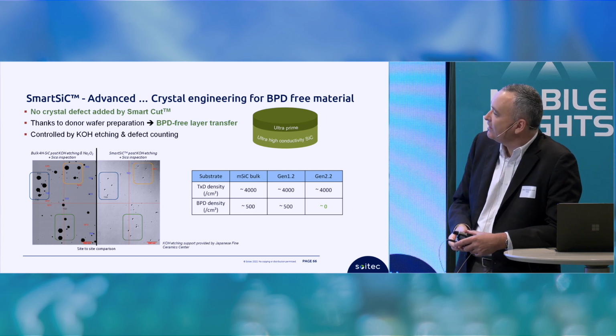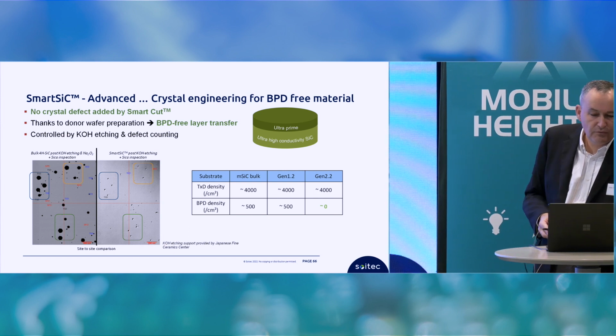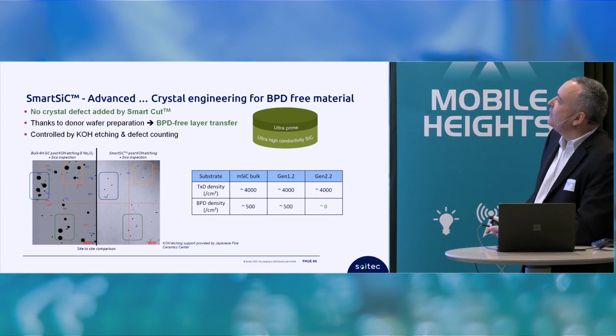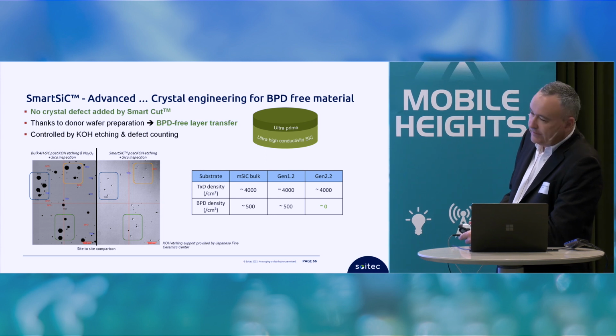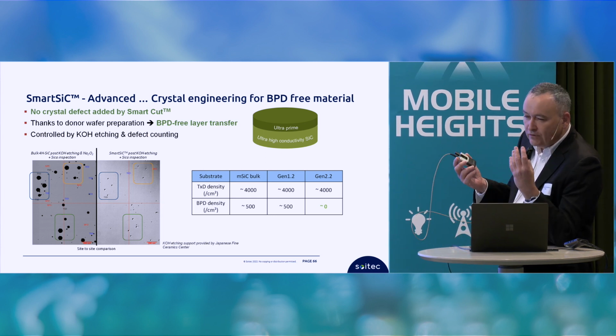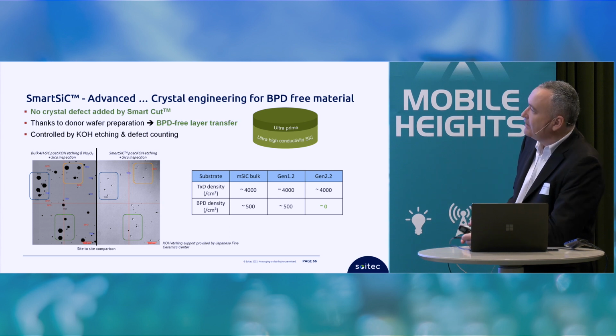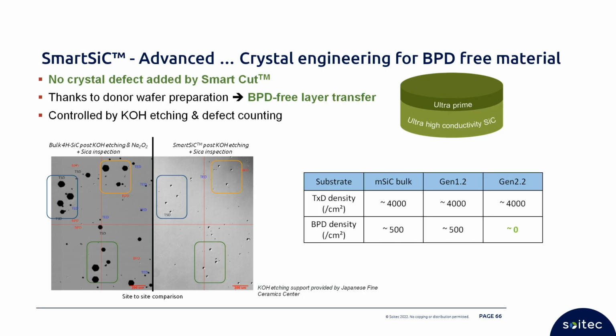When we move to SmartSiC Advanced, in addition, we add crystal engineering, and so we demonstrate that we can deliver a BPD-free material. So we know Smart Cut, in principle, does not add any crystal defect on the transfer layer. We confirm, here we have nice pictures, we confirm on SiC, if you compare with KOH decorations, the crystal defect mapping on the donor wafer and, in exactly the same position, the crystal defect mapping on the SmartSiC, you find exactly the same crystal defects. We do not generate, we do not change the crystal.